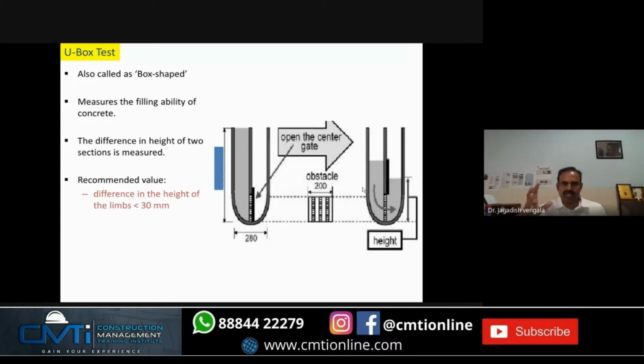In the U-box test also, there is a U-box. So you have two chambers, I can say, two limbs. One of the chambers you fill with concrete, and again, similar to the L-box, you place the gate and you lift the gate. It has to pass through the reinforcement, and it has to come to the other end of the U-box. The height difference between the first limb and second limb should be less than 30 mm. That means 3 centimeters.